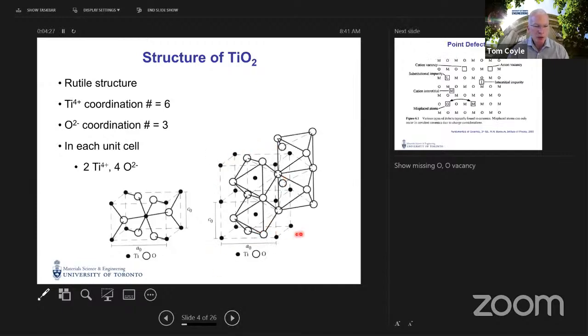And if we look at a little bit larger picture of this structure, sometimes people like to picture the structure in terms of these oxygen polyhedra, where the 6 oxygens form the corners of the polyhedra, and then to build up the structure, those oxygen polyhedra share edges in an organized way. So that's the perfect structure. Because of entropy, we don't have perfect structures. We have structures that contain imperfections and defects.